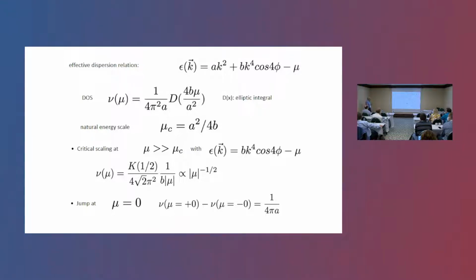What this means is basically that we know that these so-called small gamma bands are the ones who respond to magnetic field, and the rest are not so sensitive to the magnetic field. We can do a simple thing, and we can write down an effective dispersion relation, a k squared plus something k to the 4 cosine 4 phi. This exactly mimics what I showed you before. Mu in this case, if you tune this to 0, is the distance from exactly this Fermi surface topological transition that gives a higher order